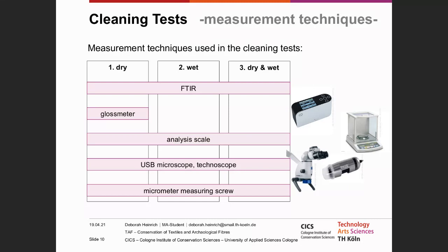For the evaluation to be as standardized as possible, I used different measurement methods. The test samples from tests 2 and 3 were too small to use the gloss meter on them. Each individual cleaning agent or combination of cleaning agents was repeated on 5 test samples. 3 measurements were taken before and after the tests on each test sample, and the mean values determined from this were then used for the evaluation.